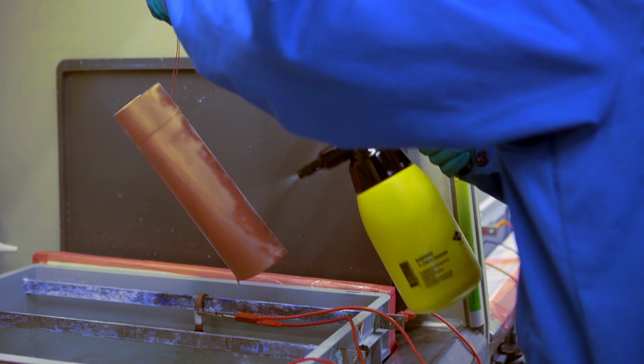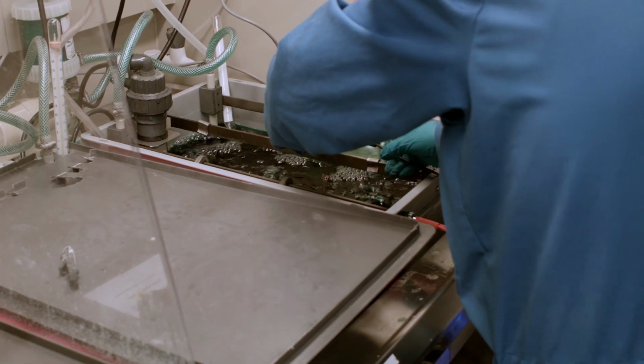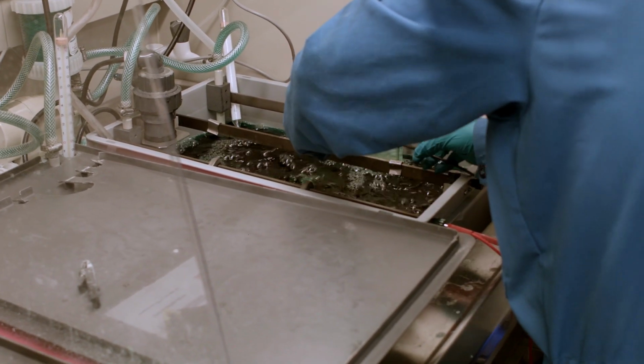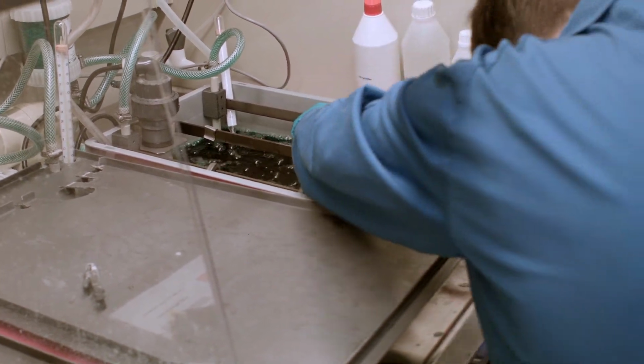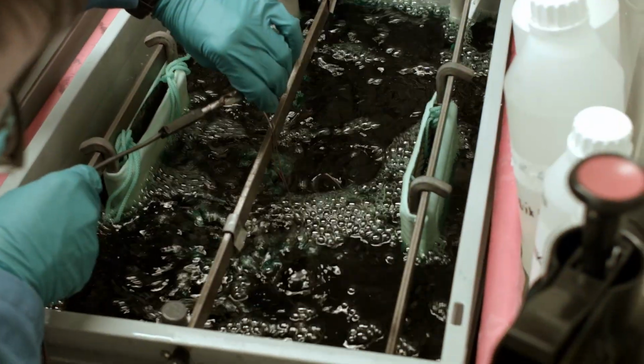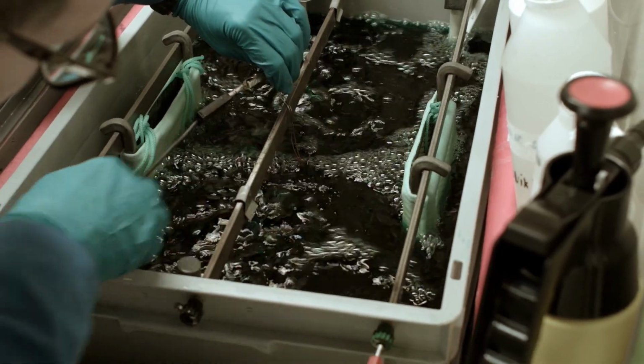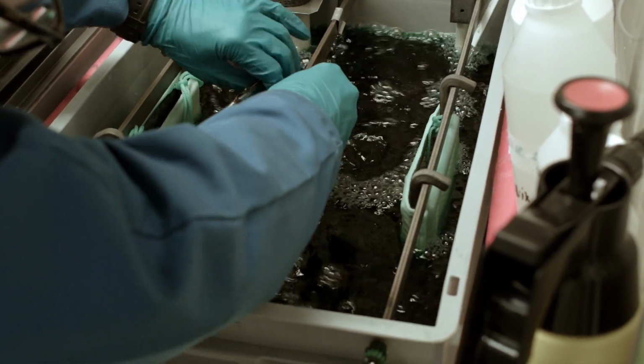After about 3 minutes in the copper bath, the part is now cleaned with water and moved to the nickel bath. To grow a sufficient nickel layer, the part is in the nickel bath for about 40 minutes, and this time we will grow about 10 micrometers of nickel.